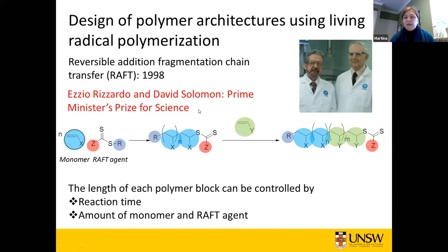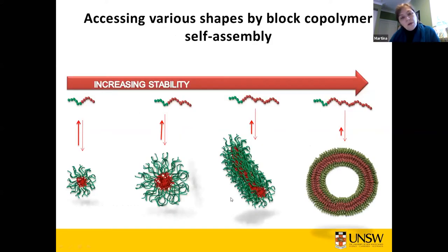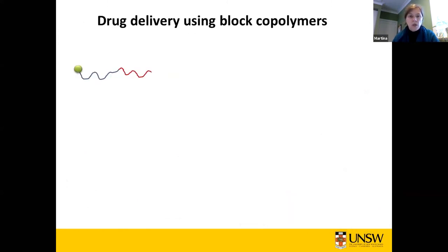So you can change the length of each block, you can change the structure, and it can all be done very, very easily. And so what people do nowadays, they actually make polymers on a robot on, for example, a 96-well plate. So in one go, you can make 96 different polymers by using techniques such as RAFT polymerization. So a massive throughput. So why is this important? It's because by changing the block sizes, you change the type of nanoparticle you're getting. So for example, if you have a very short hydrophobic block, you get small micelles. If you make the hydrophobic block a little bit bigger, you get bigger micelles, until you get to a point where your hydrophobic block is now so long that you get different aggregates. So you get here elongated structures, or you get something very much like vesicles, and because they're based on polymers, we call them polymersomes.